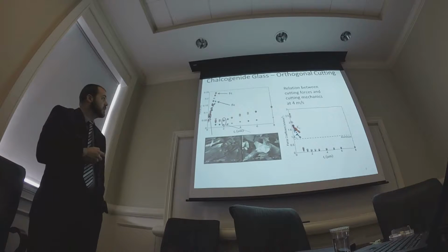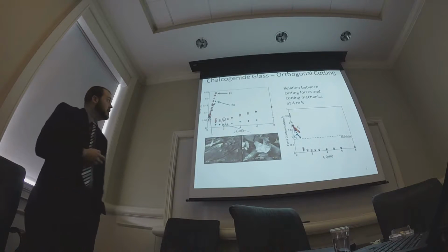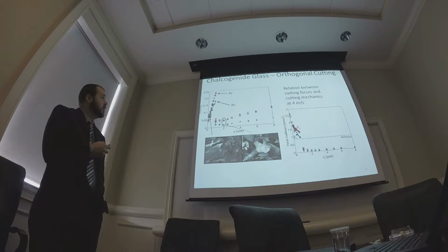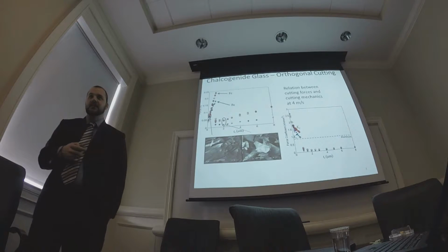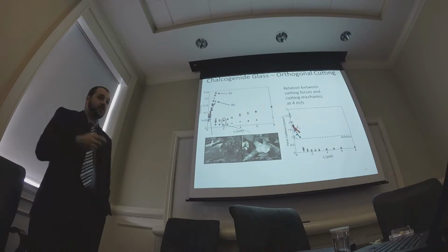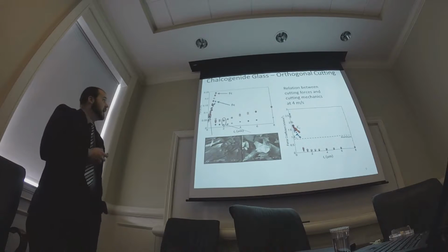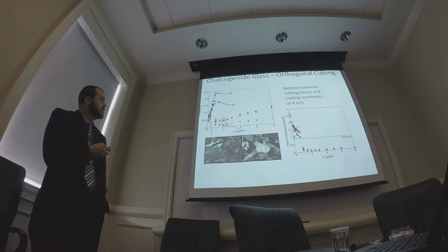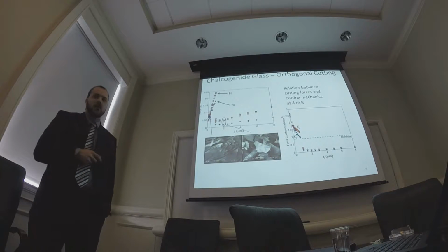As we increased our chip thickness, our force increased as we expected. But then this point at 900 nanometers - when we went from 900 nanometers to 1 micron, it all of a sudden dropped significantly, much more than we would have ever anticipated. And then the force no longer goes at this angle.